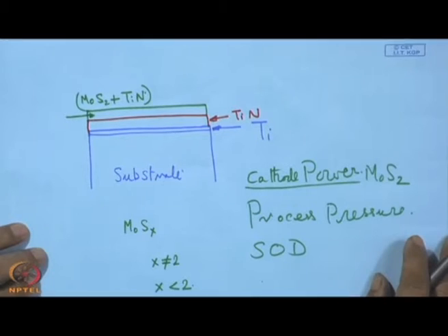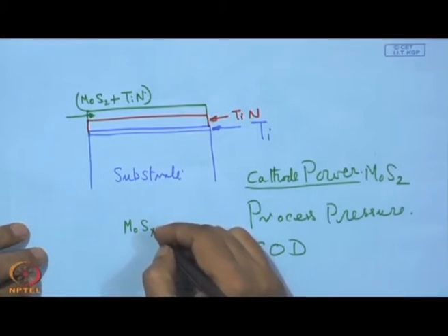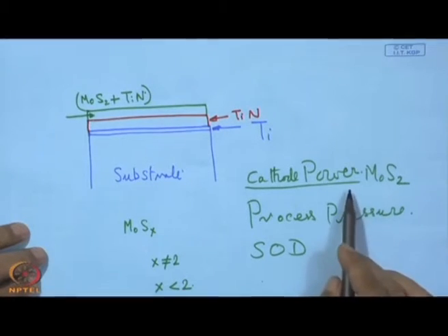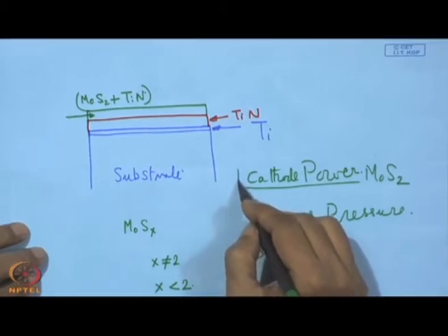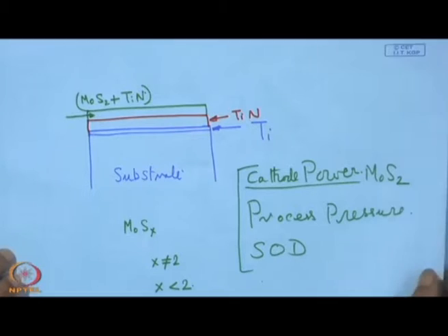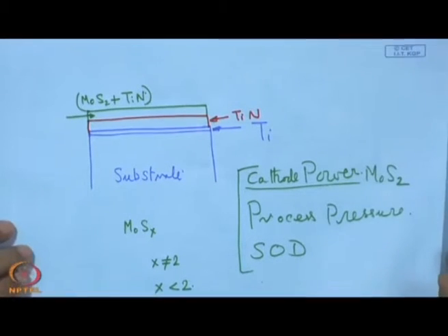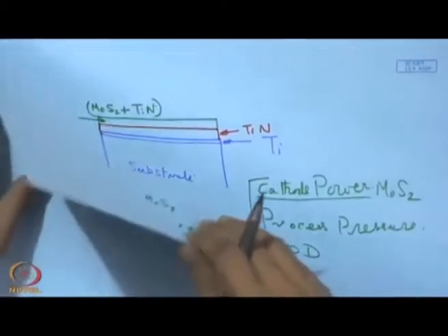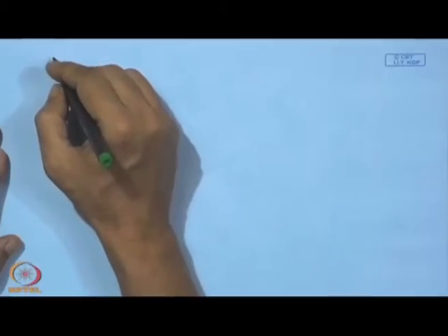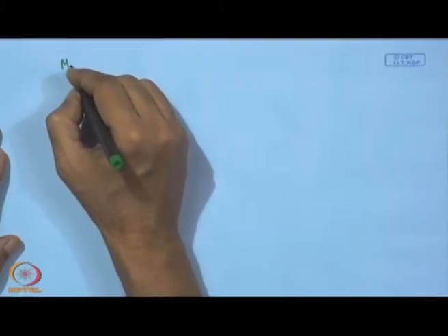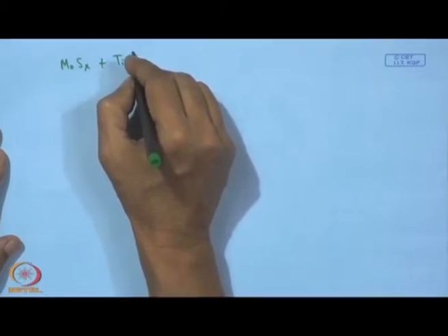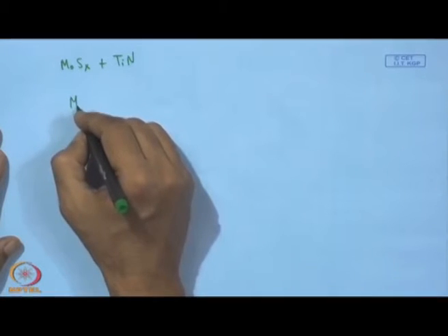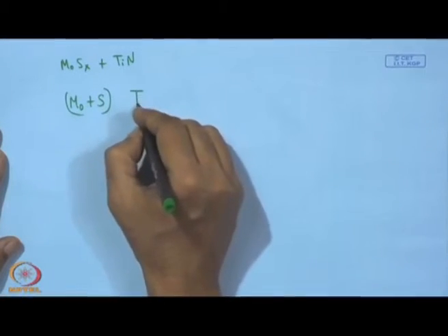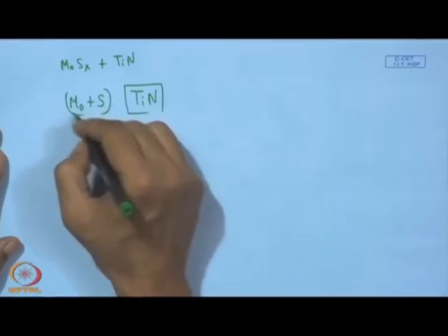So, instead of MoS2, it is more reasonable to write MoSx, where the x value depends upon the cathode power, process pressure and SOD under a given set of conditions. So, this is the MoSx coating, presented in the general form. Now, with this MoSx and TiN, the most important thing is the proportion, the atomic percentage, of MoSx plus TiN. One would be interested to know what this Mo plus S would be within the TiN. So, TiN is on one side and this is Mo plus S.